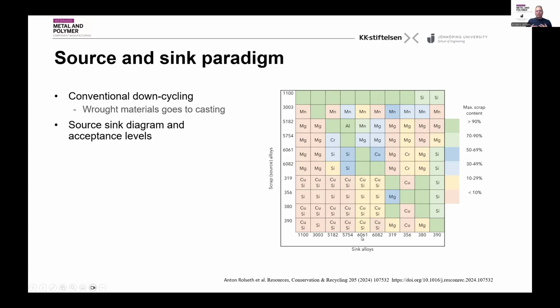So what you see in this, if you take the wrought materials, the 1000 series materials, often you have magnesium being the limiting element. And if you go down to where the source is coming from the cast alloys, making wrought materials is very challenging because you have copper and silicon being the challenges. Now, if you look at the wrought materials, we can take the 5000 series, for instance, and then choose to have the 300 series cast alloys being the sinks. Then you see magnesium is also dominant here. But because the cast alloys have a higher tolerance of these elements, you can actually increase the amount of wrought materials being used here. So that means that you go more and more towards the green range or the blue range of alloying elements. So this has been, so to say, the forgiving paradigm.